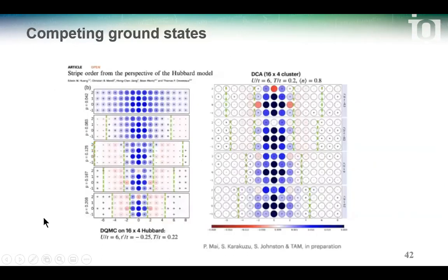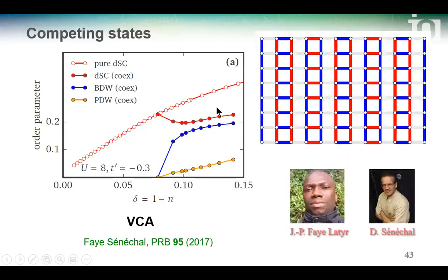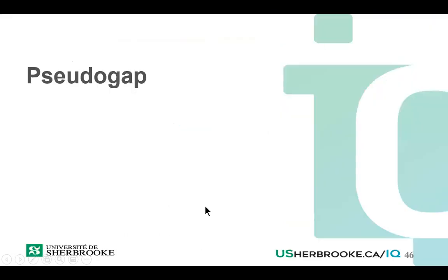Now I said that there are competing orders. So there are also charge and density waves and so on, and they are found in these large cluster calculations. But if we look at what we do locally, we still have this. So this is again the order parameter as a function of doping this time. Superconductivity itself as a function of doping. And now if you look at the competing orders, bond density wave and pair density wave, the orange line is for pair density wave and the blue line is for bond density wave, and they compete with superconductivity. So superconductivity goes down. So you see that we have these systems as well.